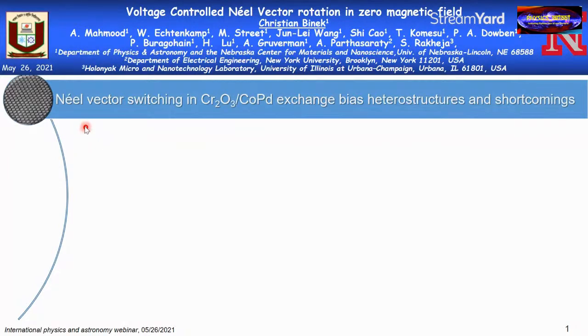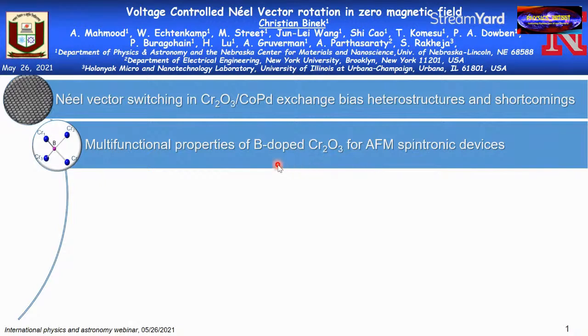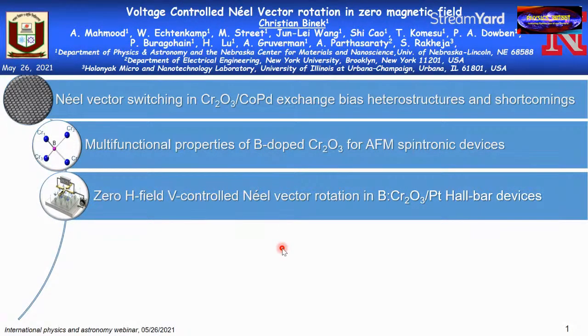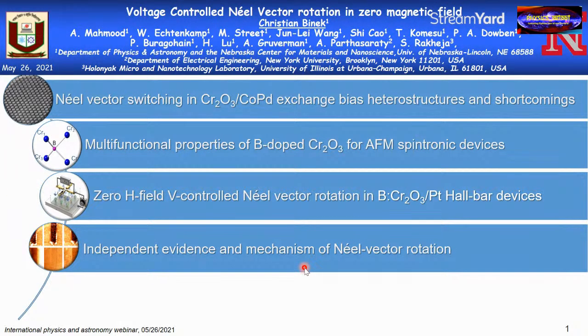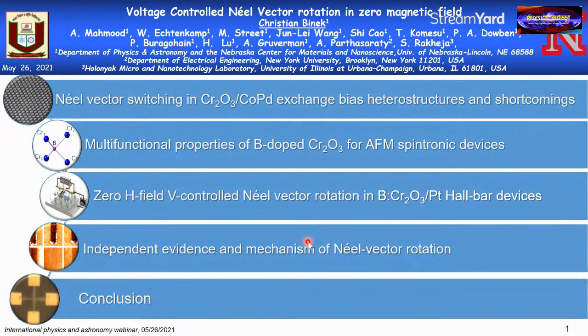We started out by doing this Néel vector switching, 180-degree rotation, in so-called exchange bias heterostructures, where one part of the heterostructure was this magnetoelectric antiferromagnetic material. That is an important piece of background information, but then I will report on the disadvantages of this approach and why we gave up on it. Then I talk about doping this magnetoelectric antiferromagnet with boron and what that does. And then I show you those switching results on Hall bar type devices, where we can achieve 90-degree rotation of the Néel vector in zero magnetic field just by voltage. Because this is such an interesting result, it's a big claim, so to say, and it requires a backup. I show you independent evidence that this is indeed magnetic switching and not an artifact. We do that by magnetic force microscopy, and then I conclude.